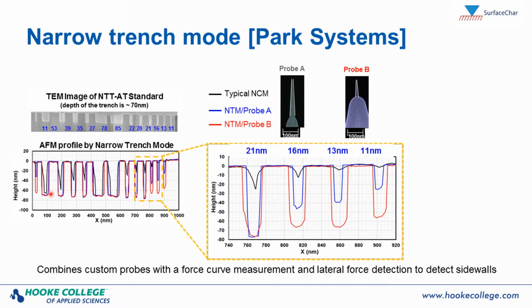And the need that this particular mode addresses is the need to be able to image very narrow but somewhat deep trenches, which are critical to metrology applications in the semiconductor industry, where they make a lot of devices with features on this order. So for example, you can see here, this is an actual sample with these trenches with the TEM image of it. And you can see the kind of aspect ratios, so depth to widths we're talking about. And this black profile is the profile of what a standard mode AFM can do, where you can see that the trenches that are especially deep and narrow, the AFM tip simply can't get in there to get an accurate measure either of the width or the depth of the trench.